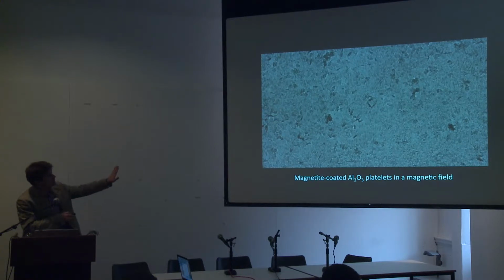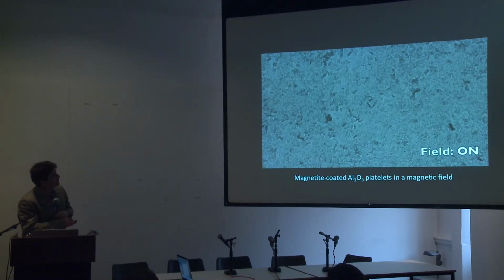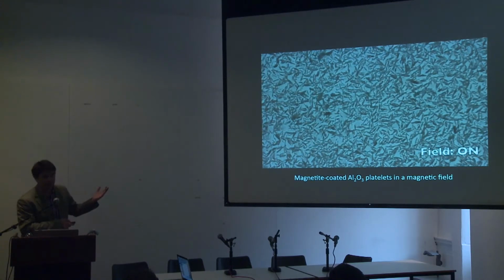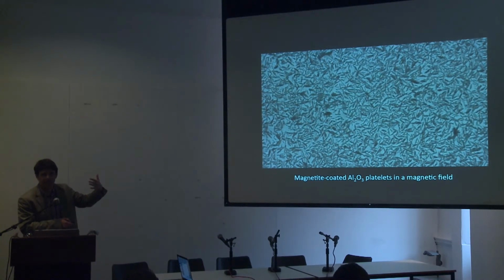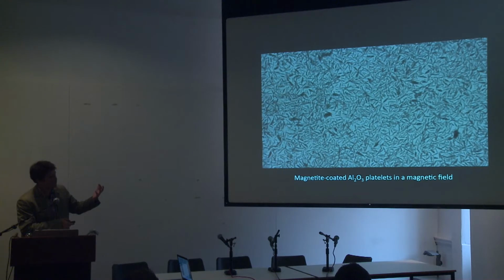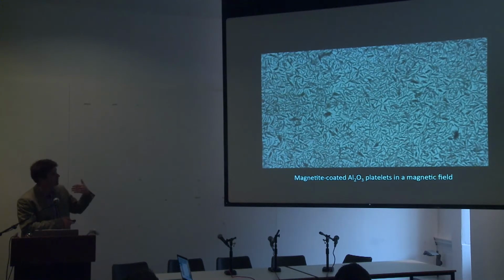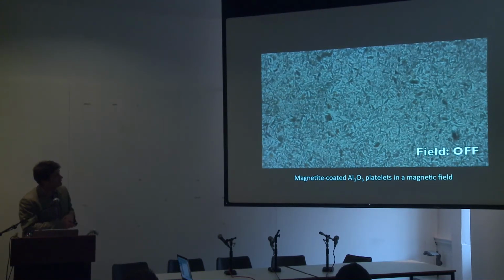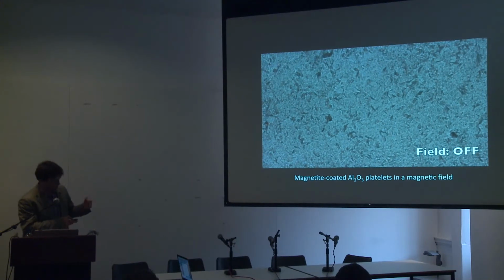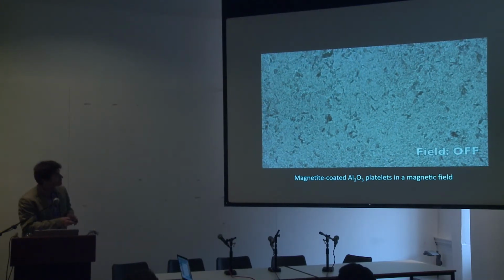So they all sit in a horizontal fashion on the glass slide, but now I'm going to apply a magnetic field out of the screen again. And you'll see that as soon as the field is on, they jump out of the glass slide, very nicely responsive. And if we turn off the field, you'll see that they all get back because of gravity. So this works very nicely.